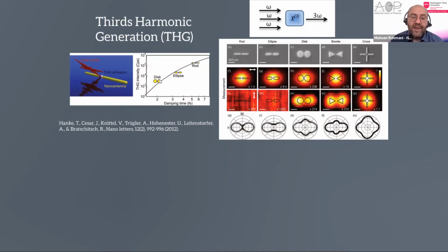As you can see here, for different types of dimers, when the dimers are disks or ellipses or rods, you have different nonlinear signals, third harmonic generation of course. But for the rods, we have the highest one, which is something that you don't see at microscale, because at microscale, the more material we have, the higher the signal intensity and efficiency. But when you come to nanoscale, the material alone is not the main player. There are so many other factors and degrees of freedom, and one of them in plasmonics is this near field enhancement and these hot spots. As you see there, these plasmonic resonances can really enhance the nonlinear signal, which wouldn't be possible at macro scale because we don't have this phenomenon at macro scale.